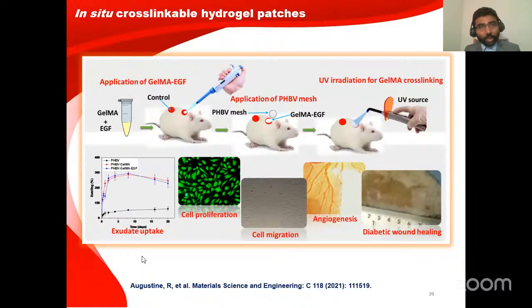Similarly, we generated a hybrid hydrogel patch. In this approach, we used GelMA, that is gelatin methacryloyl, loaded with epidermal growth factor, which is a very potent growth factor that can help in the wound healing process. Then we loaded such material on the wound. Then we applied a secondary PHBV mesh, that is an electrospun mesh, over that wound with hydrogel. Then we applied UV irradiation. Then that hydrogel along with the porous scaffolds were integrated into the wound. Then we allowed for wound healing, and we found that a very high rate of wound healing was observed when the protective hybrid patch was over there in the wound.